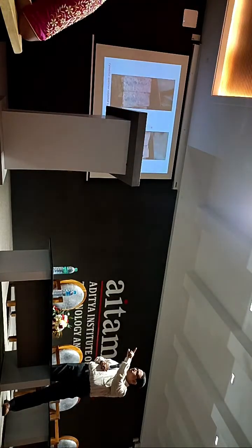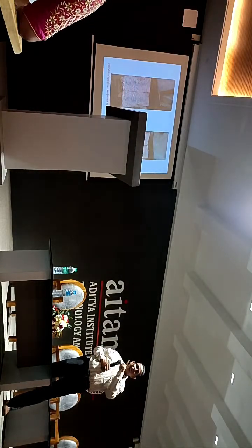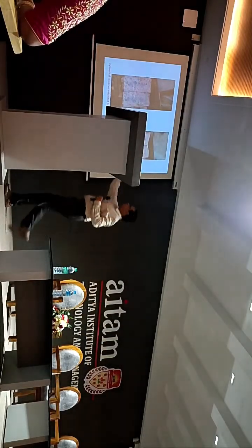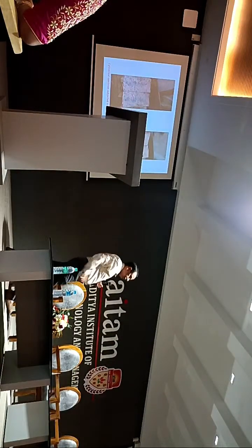You see on the left-hand side you have 700 exposure, right side 800. What is the difference? Up to 700 there is core concrete which is still not changing its color. Conventional color is there, isn't it? The core concrete, you can see, is grayish in this central portion. But when it is 800 exposure, even the core changes to a different color.